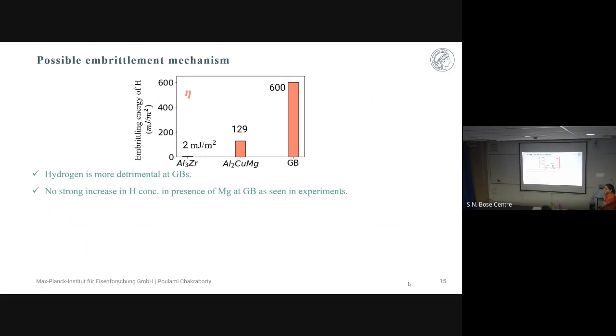In other words, if you see any crack surface of aluminium, you shouldn't have any Al3Zr on the crack surface. No, it is mostly near the grain boundaries. I have shown, I will go to the picture maybe later on, the first picture which I started with, there near the intergranular crack, there was this grain boundary thing, absolutely adjacent. I will go to it after the talk.